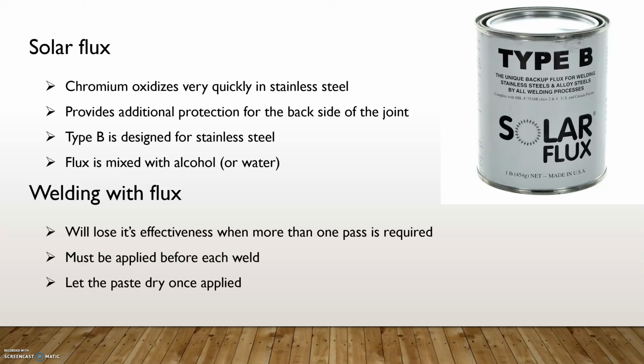Using solar flux is a paste that helps protect the backside of joints that are too big to purge. Type B solar flux is designed for stainless steels and is better mixed with alcohol solutions so that a chemical reaction can happen. Solar flux will lose effectiveness after 1 pass, and it must be dry before welding. So if you're doing multi-pass welding, you would do 1 pass, and then you would have to clean the backside, wire wheel it, and apply another layer of solar flux.